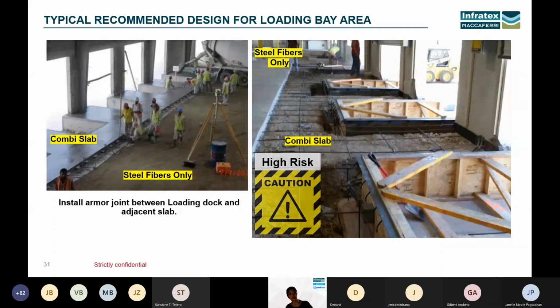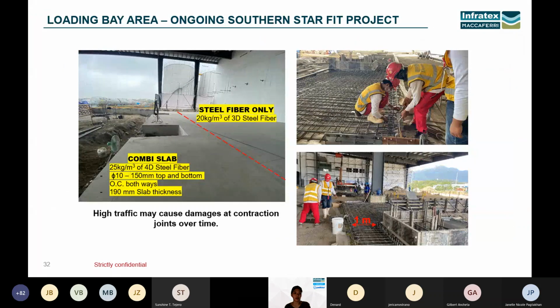So we use combi slab for the loading docks, and for the adjacent slab, we only use steel fibers, 3D fibers only. Okay, so this is the actual picture of our project in Southern Star. For the combi slab on the loading dock, the design is 25 kilograms per cubic meter of 4D steel fiber with 10 millimeter rebar, 150 millimeter top and bottom on center both ways. So it has a slab thickness of 190 millimeters.